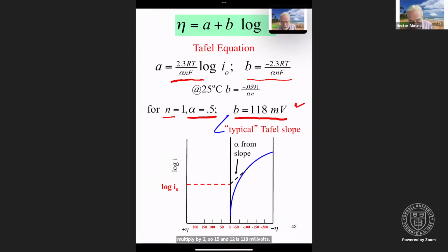And what that means is under these conditions, in order to increase the current by a factor of 10, you need to apply an overpotential of 118 millivolts. The larger the value of the Tafel slope, the more sluggish your reaction is. And people will make big arguments based on the Tafel slope, which can be useful, but it can also be a little misleading and confusing.